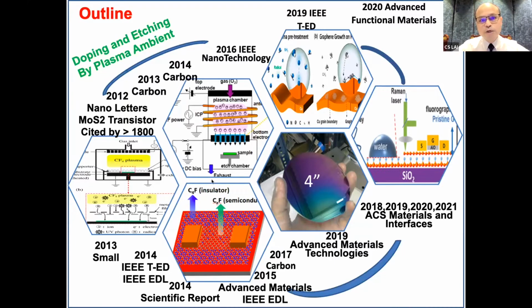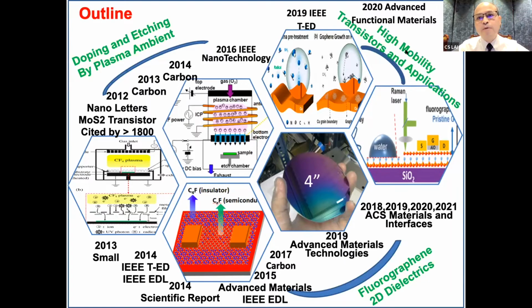And after we just prepare the special techniques for doping and etching, we try to scale up to 4-inch wafers. So in our lab, in our university, we can just have a scale up process for the 2D materials, especially for CVD. Even though it is a small grain size, but it's very possible for the future applications. So we just prepare 2D dielectrics. I will introduce you later, and we call it the fluorographene. If we just have the strong fluorine doping on graphene itself, the graphene will transfer to fluorographene. And eventually, we just using the fluorographene to prepare the high mobility transistors and the possible applications.